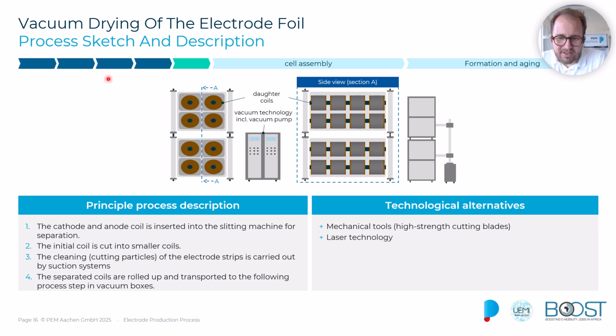So how does it work specifically? The chambers are evacuated from air, so the pressure is reduced, and then heated up to 120, 160 degrees for 12 to 30 hours. And under the low pressure, the water boils up easily, and essentially you want to have no residual moisture coming out of the coils in this process. Normally you then can also flood the chamber again with inert gas to avoid adding again some new air.